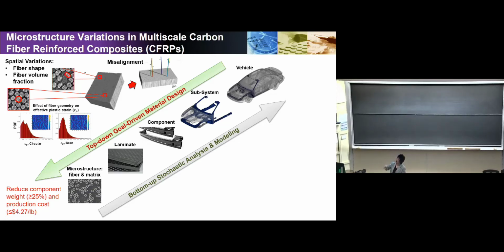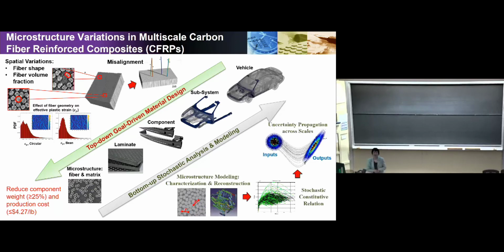And if you look at the small scale level, those are images actually taken by Ford that show that the fiber shape can be different. They're usually not round, and that could lead to damage behavior. The lower part shows the stress distribution for circular versus beam type shape. You can see that with beam type, it's more prone to damage. And there are thousands of fibers if you take out a single point, and there's a misalignment issue. There's literature discussing how misalignment could lead to damage behavior at the end. So how do we take into account this kind of variation? That's the subject that I want to discuss today and show you some of the methods.